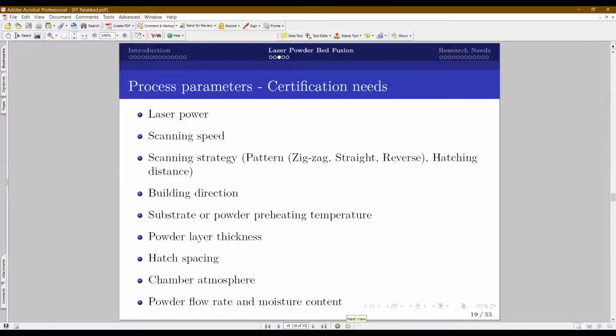Next comes the process. There are about 100 plus parameters. The major parameters are laser power, scanning speed, scanning strategy, build direction, build substrate temperature or powder temperature, layer thickness, hatch spacing, the ambience we use, whether nitrogen or argon or any other, powder flow rate and moisture content. Then there are some parameters about the recoater blades and other sensor based information. We capture everything during the first development, and if the first development is successful, that will be frozen till the end. As long as we follow that, only then will the certification be awarded.